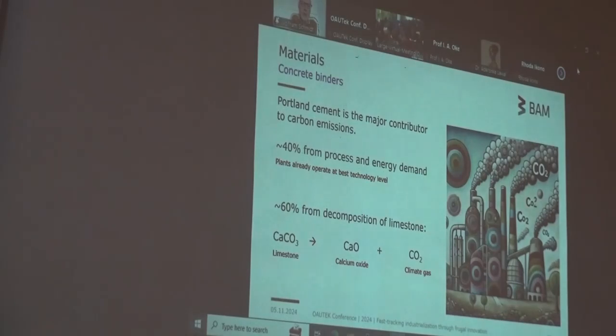And about 40% of the carbon emissions from cement are coming from the operation of the cement factory, from the high temperature, 1,450 degrees Celsius is required to burn it, and also for transportation, grinding, and so on and so forth. But here we can't really optimize anything anymore, because those cement factories, the modern ones, are operating at very, very high efficiency level. And another 60%, if we think about Portland cement as a binder, are coming from the decomposition of limestone. So we have to convert calcium carbonate into calcium oxide, and what is released in this process is CO2. It's just an inherent chemical aspect of the processing of cement.